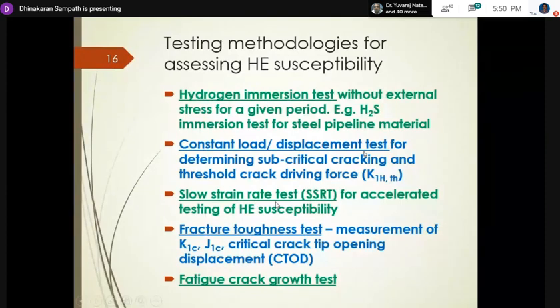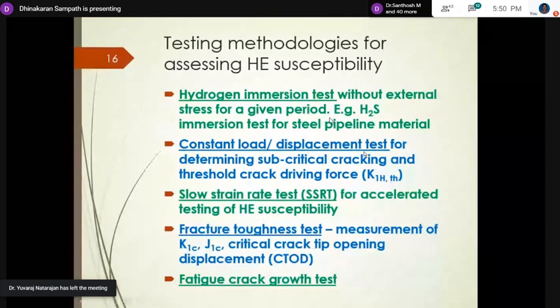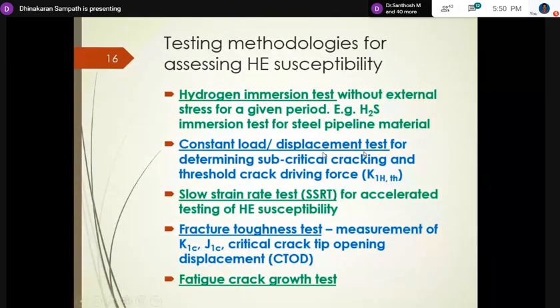For accelerated testing, this one will take a lot of time, and they expose it for a certain period depending on the severity they need. Slow strain rate is an accelerated test. It's very easy, which is why most industry people prefer it to get a quick result, at least in the screening stage. That means ranking: when they have a lot of materials on their wish list, they test them quickly, rank them, and then go to the next stage of material selection.